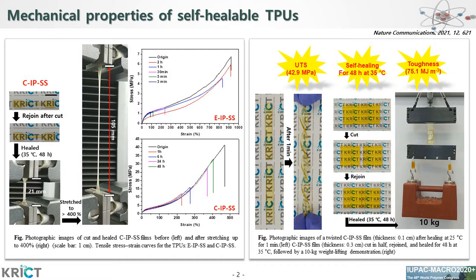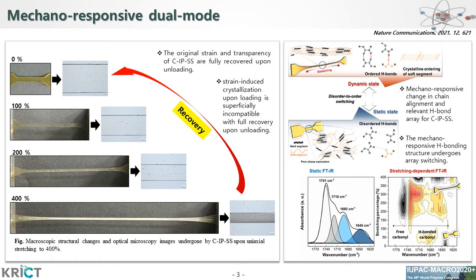Even after 1 minute of recovery at room temperature, a cut and rejoined film was able to withstand manual drawing and twisting. At 400% elongation, CIPSS becomes translucent due to the formation of crystallites. Interestingly, the original strain and transparency of CIPSS are fully recovered upon unloading. Strain-induced crystallization upon loading is superficially incompatible with full recovery upon unloading. The unusual strain-induced crystallization of CIPSS is strongly correlated with the reversible disorder-order switching of the mechanoresponsive hydrogen bonding array.